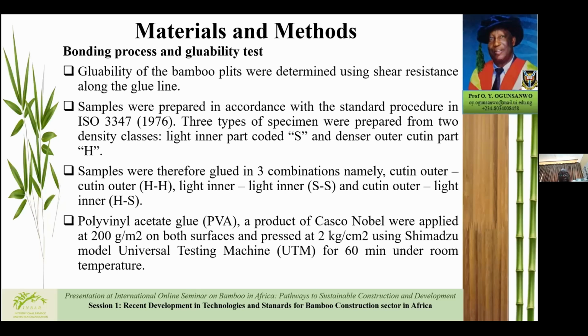Using the special product of Casco Nobel, the glue was applied at a rate of 200 grams per meter squared on both surfaces and pressed at 2 kg per cm square using Shimadzu model UTM. This was done for 60 minutes under room temperature.